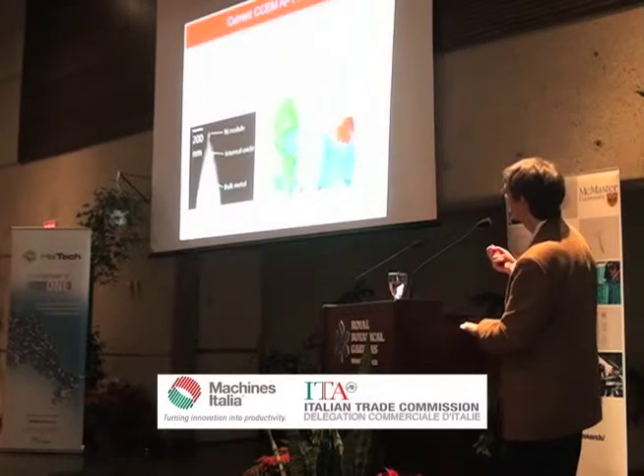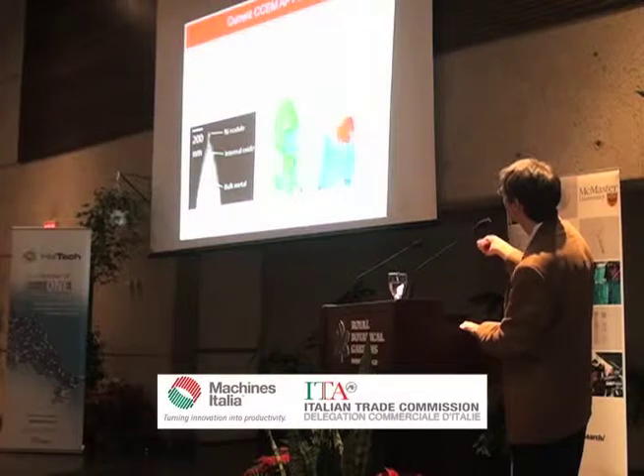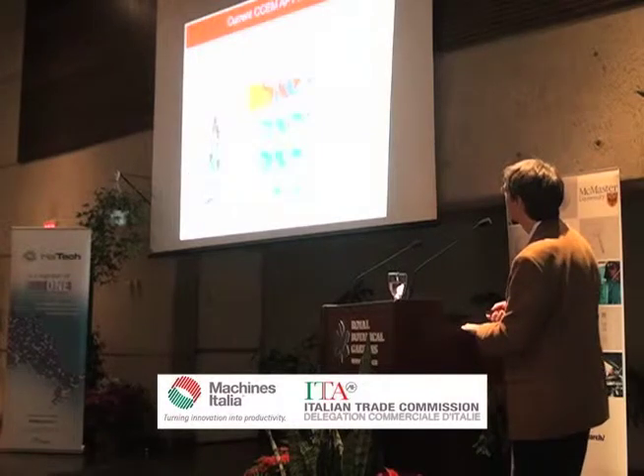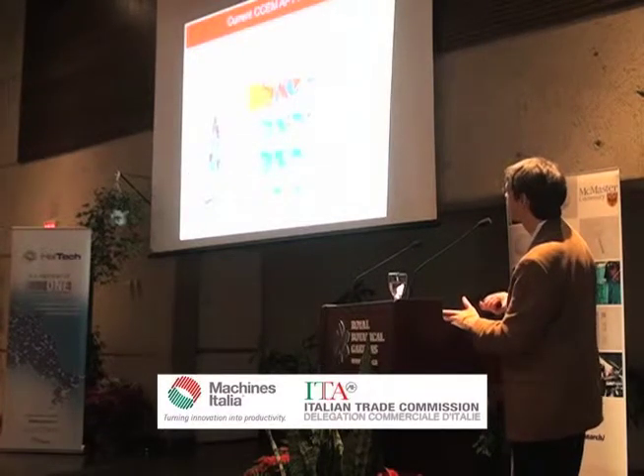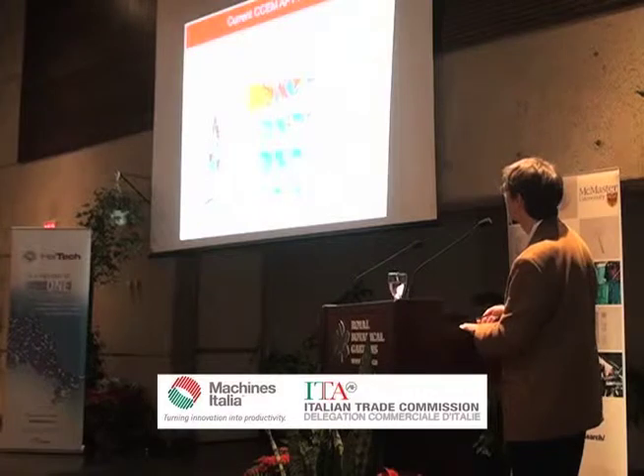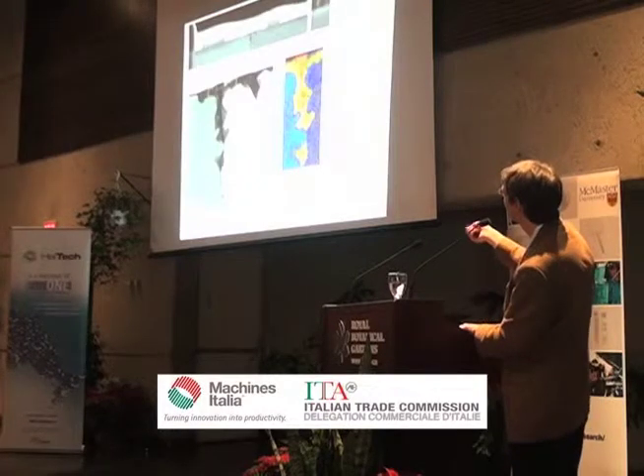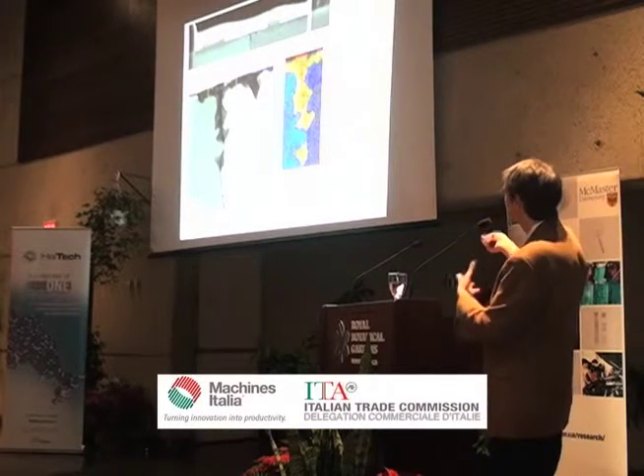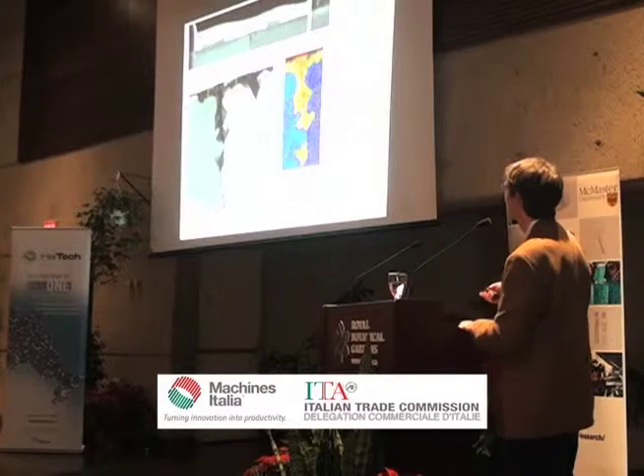And with the atom probe, we can determine that you have these oxides and we have nickel present. So it really provides information on how these oxides form, and we can determine the composition of these oxides and their spatial distribution. And then we can look at these cracks, very tiny cracks in the middle here, and the formation of chromium carbides, chromium oxides at the grain boundaries.